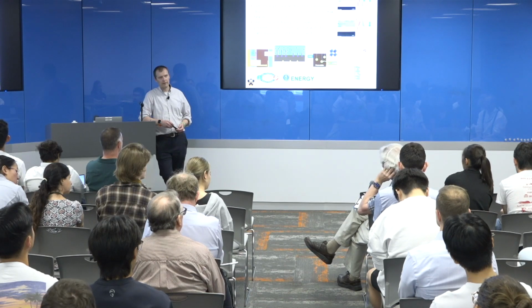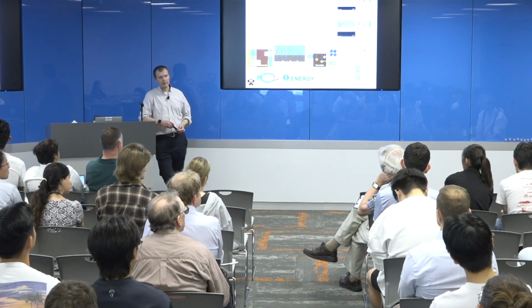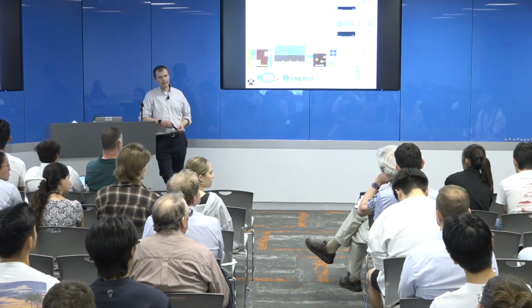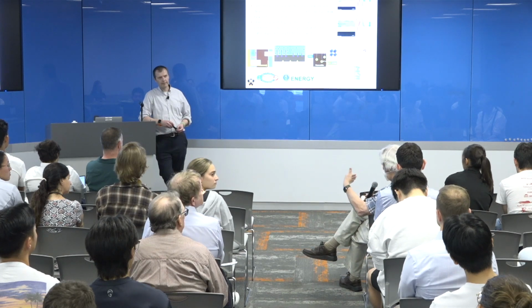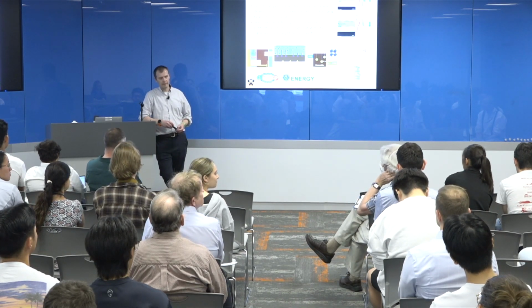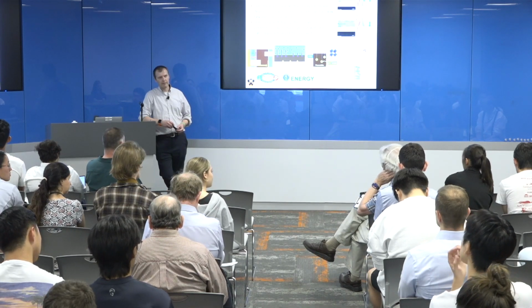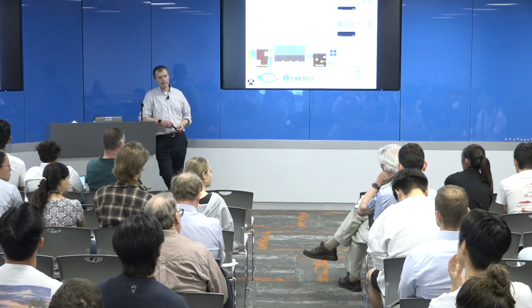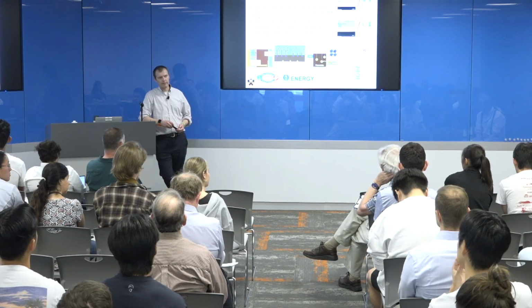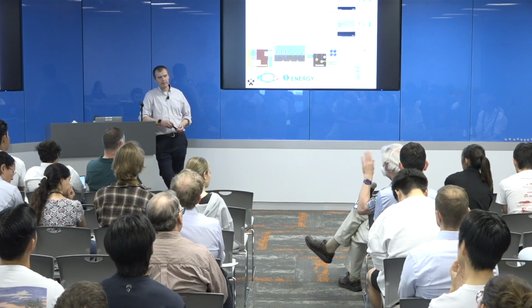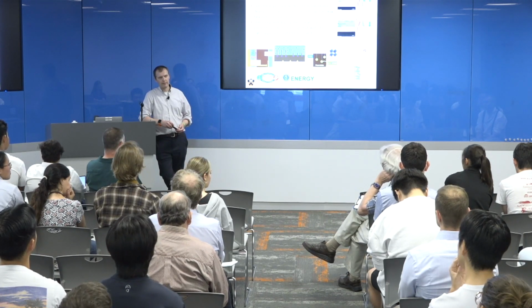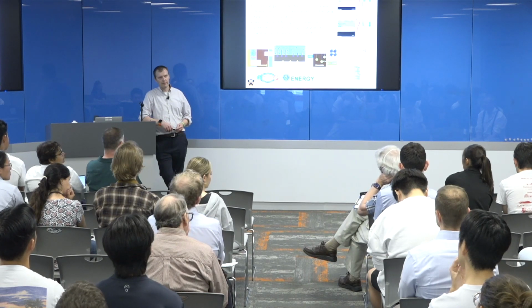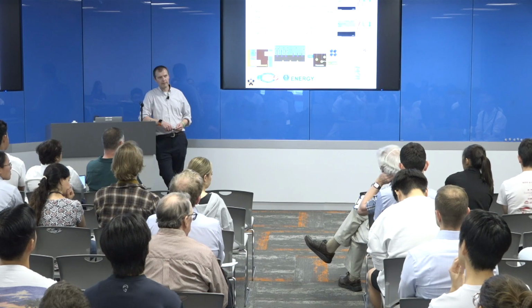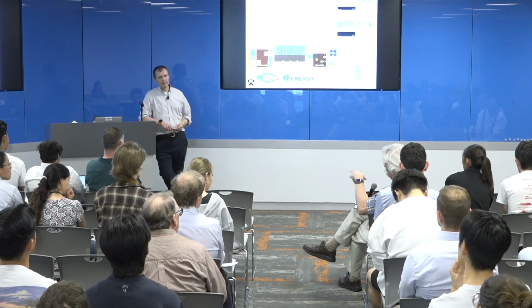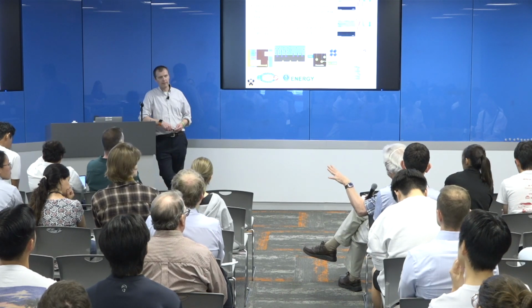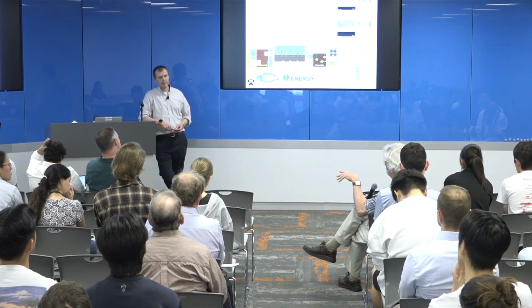And I think you have to be aware of this. You can try to identify the species, but you can only really understand the species of defects you have in the system, which also can lead to the transport phenomena you see. If you think about the reaction with the cations and anions and other defect populations in your perovskites, it's a very complicated system. And I resonate with your first point there, but I think there has to be a lot of defect spectroscopy done here to really understand what's happening in this system. It doesn't change the calculus of charges, transport, and so forth, but it does change the way you think about the diffusion of these defects a lot.